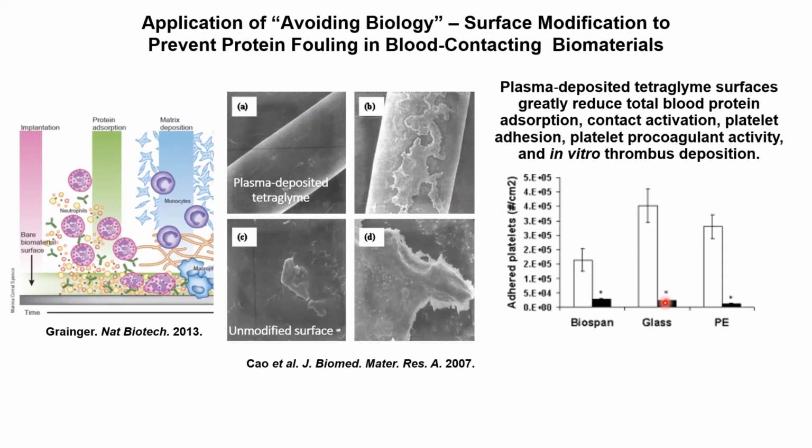Now, for those of you that have taken biomaterials classes, you know that long-term, it's very, very difficult to prevent any cell adhesion to the surface. This is why right now, if we go below about a 3 to 5 millimeter size of a vascular graft, we cannot use a synthetic material. And we still, for a CABG procedure, have to take a vein out of your leg and put it into your heart. It's because, after 60 plus years of looking at this, we can't prevent the adhesion.